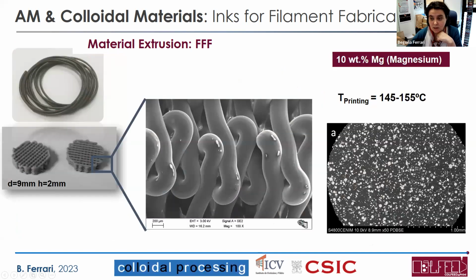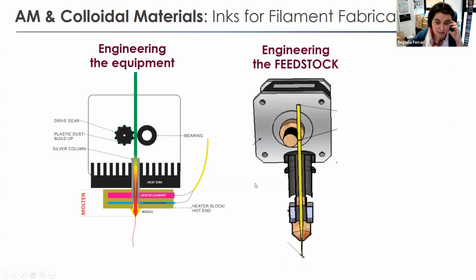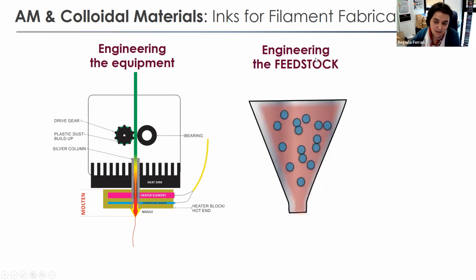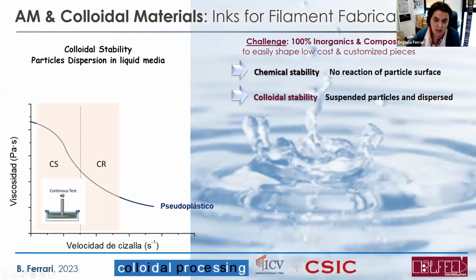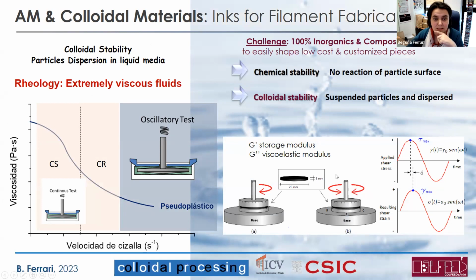And in this material, we are able to put many kinds of particles, magnesium, for example. And thanks to zeta potential and rheology studies, we can isolate the particles inside the polymeric matrix. You can see here all the particles alone in the polymeric matrix, and we can shape any kind of piece. We can engineer the equipment, but we can also engineer the feedstock, trying to avoid clogging of the nozzle, creating links between the particles and the polymeric matrix,